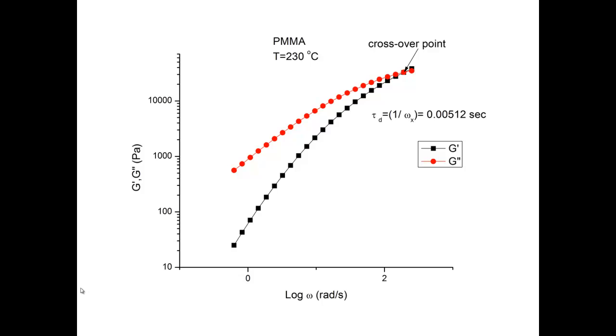Now, if you look at the existing understanding of flow, a melt is determined from its value of viscosity at a given temperature and pressure. In a rheometer we determine its longest relaxation time, meaning that it has relaxed totally from any previous deformation if we rest the melt for a time longer than the longest relaxation time. This time is called the reptation time, determined by the reptation theory, and it is tau sub d. We know that the crossover point of G prime and G double prime is a good way to determine its value.